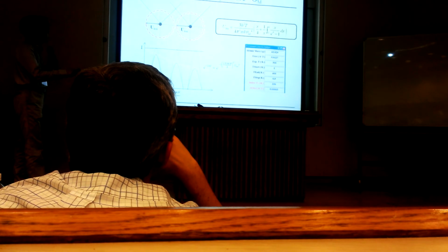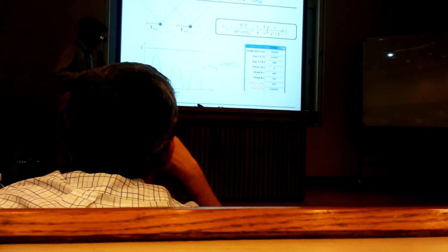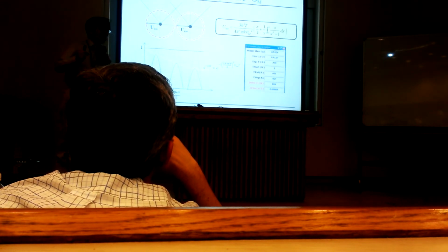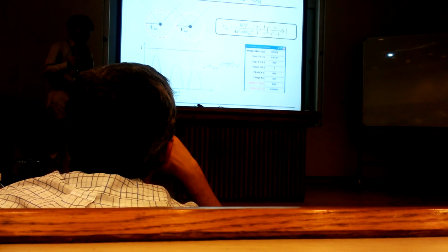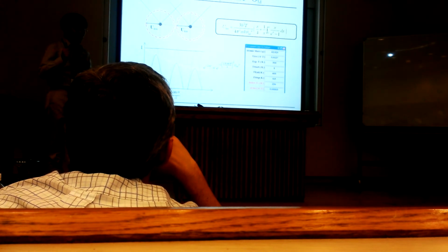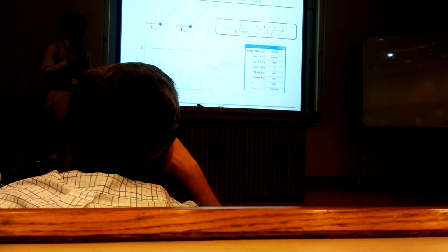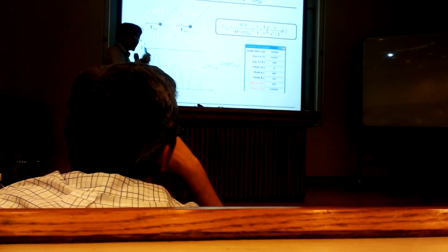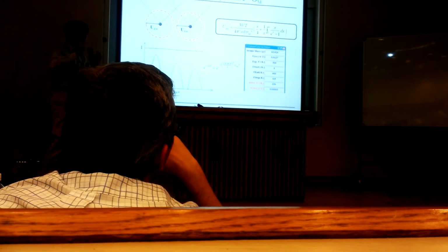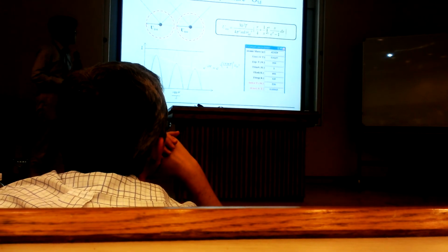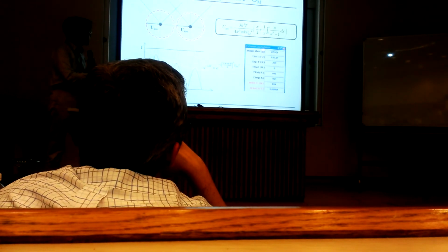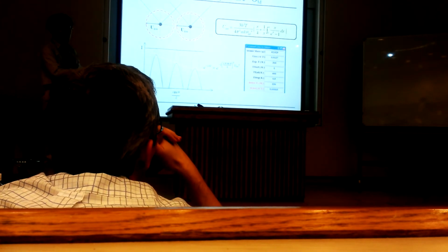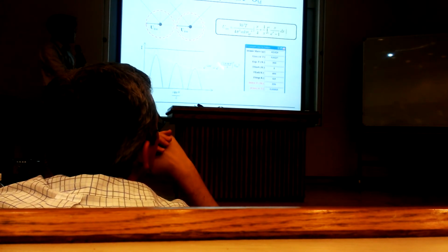This X-ray Debye temperature is usually used in X-ray diffraction. They can calculate the X-ray Debye temperature, but that's very different from the Debye temperature, because the X-ray Debye temperature takes into account the average vibration frequency, but not the cut-off vibration frequency. That's quite different. But you can also calculate some speed in the crystal by this method.